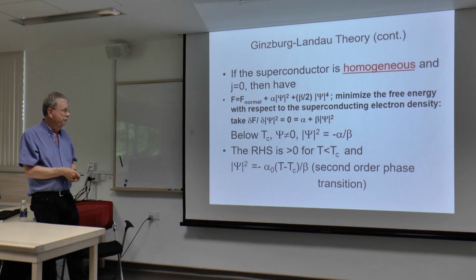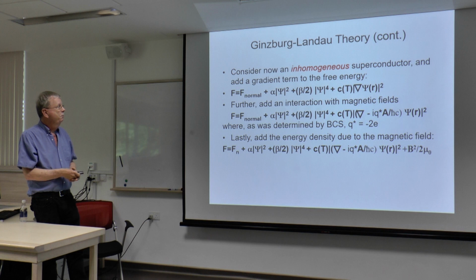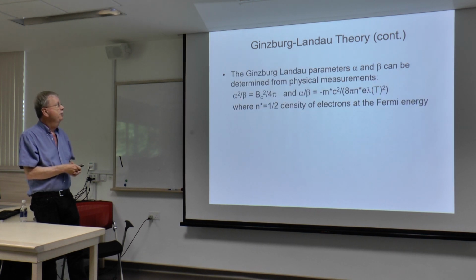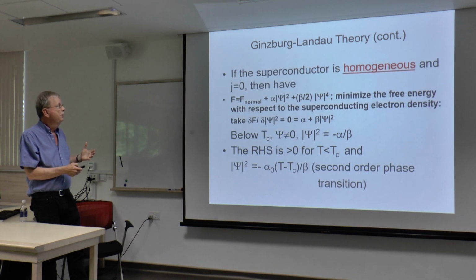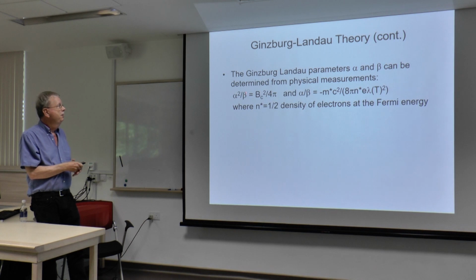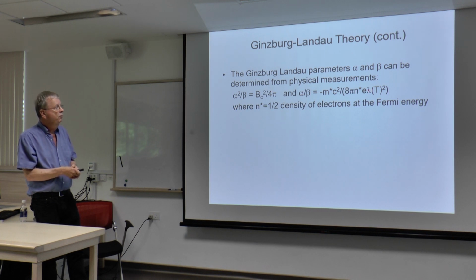So this turns out to be an important ratio of parameters. And of course, if I showed you that important ratio of parameters without telling you where it came from, you'd want to know where it came from. But when you introduce the magnetic field, it looks like that. But anyway, here we go. If you take the ratio from that original Ginzburg-Landau equation, where alpha is the coefficient of the psi squared term, and beta is the coefficient of the psi to the fourth term, if you take the ratio this way, this is condensation energy, and if you take this ratio, it involves 1 over the, wait, penetration depth, thank you.